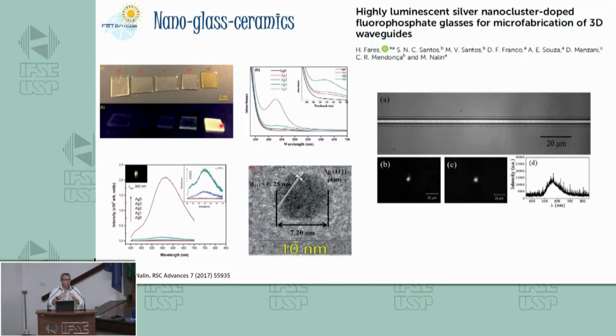So controlling the power of the laser and the speed at which you write, we can obtain very nice waveguides like this one. And this is the measure of the light when you shine a UV light here. So we excited this waveguide with the UV light, and then we saw the white light come out at the end of the waveguide. So we can generate and guide white light into the channels.